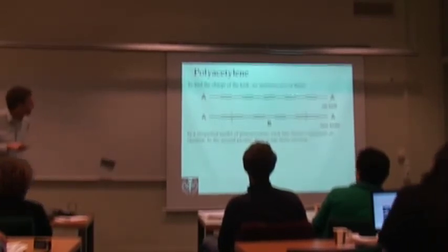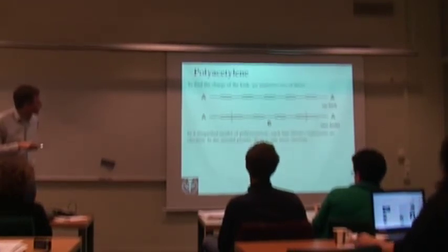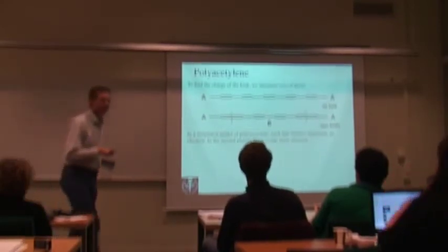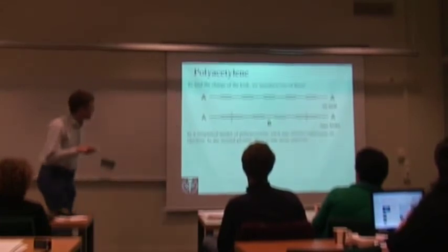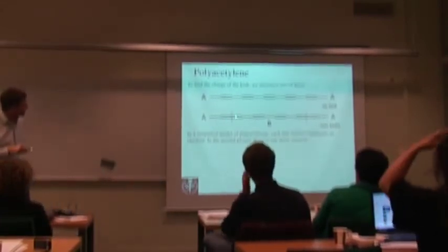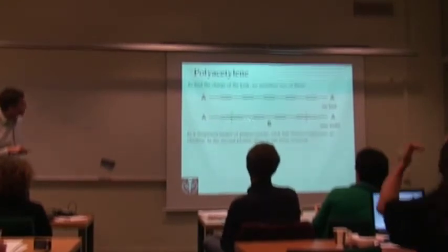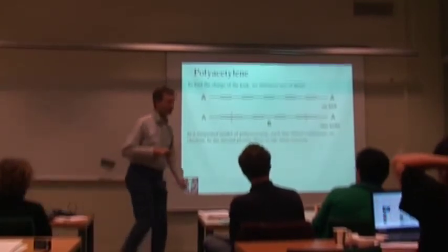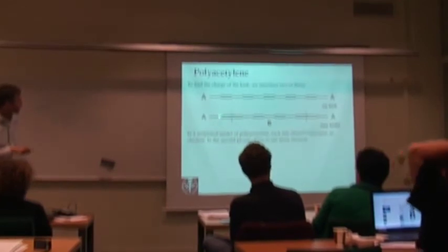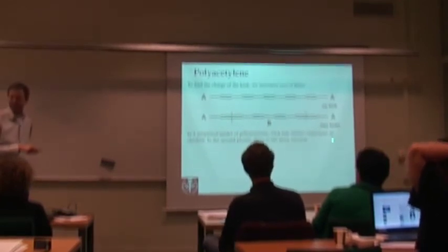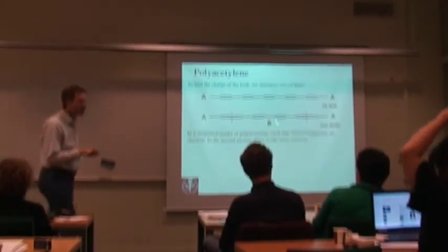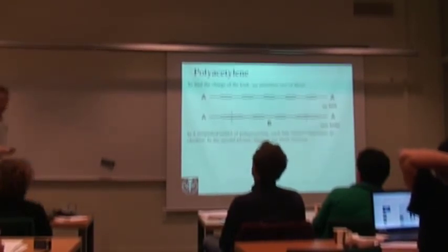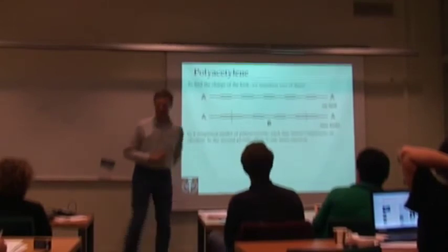Now I see that the second picture has one charge more than the first picture, so there's one electron more in this picture than in the first. But I also see that there's some localized charge here, and some localized charge here. These charges can move around freely by just hopping off the electrons. And this kink clearly looks exactly the same as that one. So the only conclusion, if I count the charge, is that this thing has a charge of a half. Isn't that cool? I think this is great.